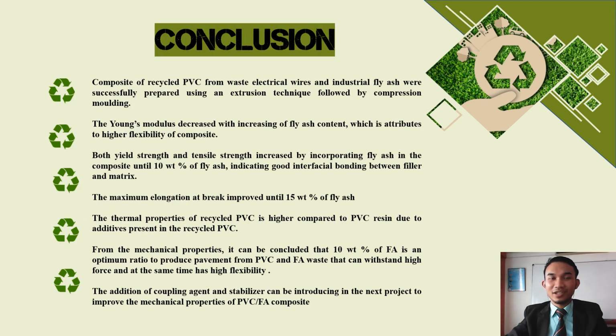In this part, I will share the conclusion of my project. The composite of recycled PVC from waste electrical wire and industrial fly ash was successfully prepared using an extrusion technique followed by compression molding. The Young's modulus decreased with increasing fly ash content, which is attributed to higher flexibility of the composite. Both yield strength and tensile strength increased by incorporating fly ash in the composite until 10 weight percentage of fly ash, indicating good interfacial bonding between the filler and matrix. The maximum elongation at break improved until 15 weight percentage of fly ash.